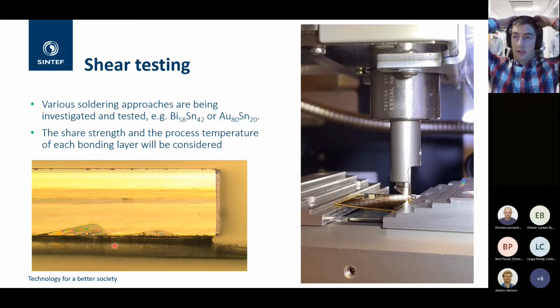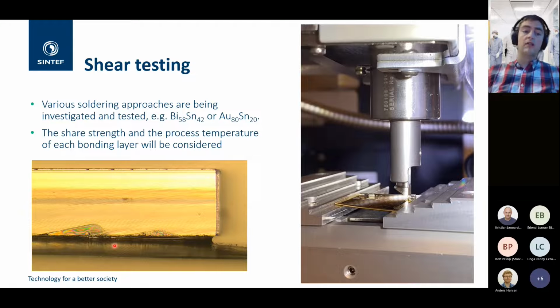So for the moment, we started our work on solder, and we are testing two types of solders. And since we need full control over the thickness, the uniformity and the planarity of the system, we end up using preforms of bismuth tin and gold tin solder. We are basically at the moment bonding several dies with different parameters to evaluate the planarity and the strength, as you can see on this second image here, where we do a shear testing of the bonded die.